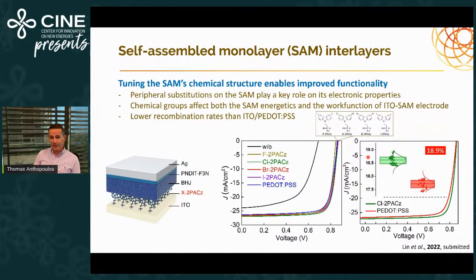So my belief personally is that SAM interlayers are here to stay, and I believe they will provide solutions which are very important for the field of OPV in general. More recently, and we published it I think a few weeks ago, we were able to use the same SAMs for creating hole injecting layers for highly efficient perovskite light-emitting diodes, essentially replacing PEDOT:PSS altogether. And by replacing it with a self-assembled monolayer hole injecting layer, we were able to improve the efficiency of these perovskite LEDs quite a lot.